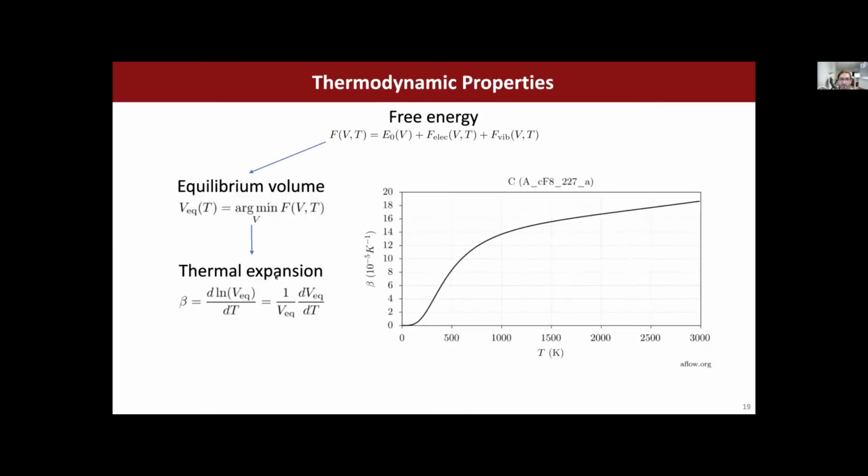And next step, since we have a volume as a function of temperature, we can actually extract a very important parameter, which is thermal expansion. And for that, you just do a logarithmic derivative of volume. And here is an example of carbon in a diamond structure.